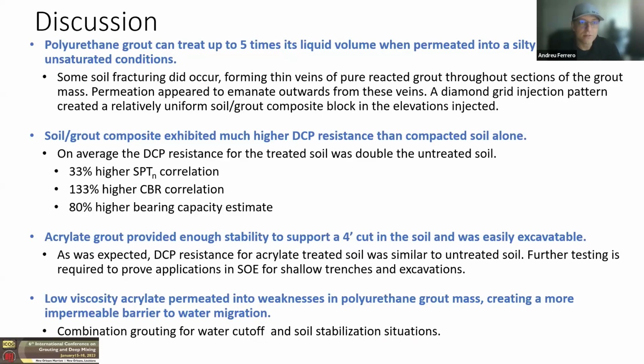So for discussion, the main points are that the polyurethane grout can treat up to 5 times its liquid volume when permeated into silty sand in shallow unsaturated conditions. Some soil fracturing did occur, forming thin veins of pure reacted grout throughout sections of the grout mass. Permeation appeared to emanate outward from these veins. A diamond grid injection pattern created a relatively uniform soil grout composite block in the elevations injected. Typically, we found that it was around 90 to 95% coverage rate, with some edges and corners not getting fully covered.